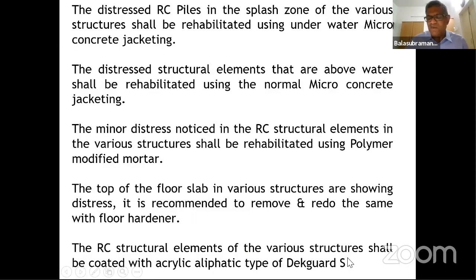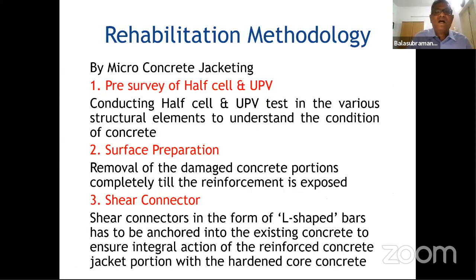Dekguard is a commercial name for Fosroc. So they can use anything, a silane siloxane coating, acrylic aliphatic type. And then the methodology is basically to remove the damaged concrete portion. For that, based on the chloride levels, chip open the unsound concrete, and then provide shear connectors, because the old concrete has to bond with the new concrete. You have to provide shear connectors.